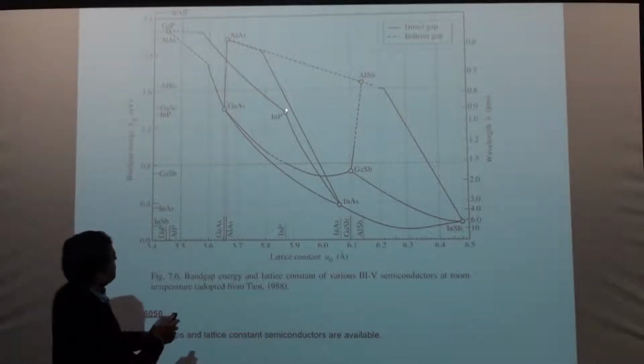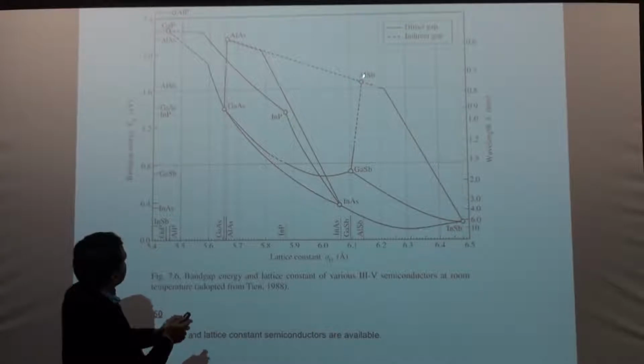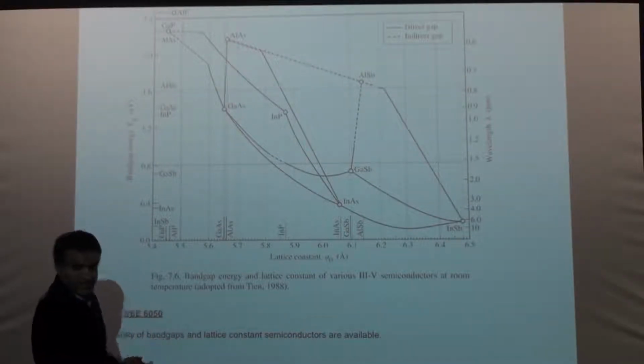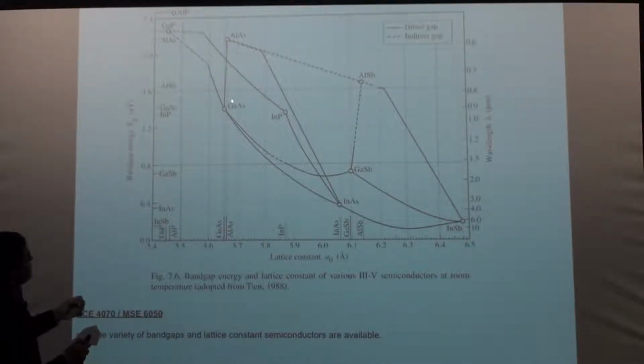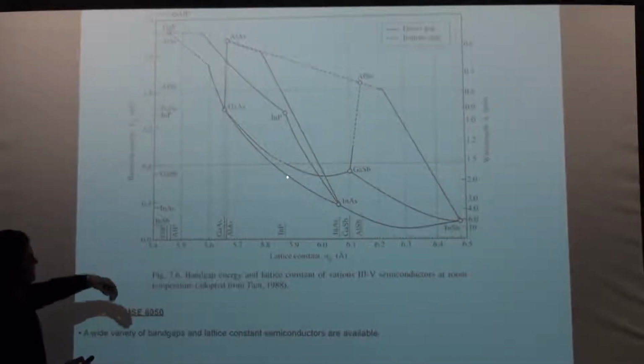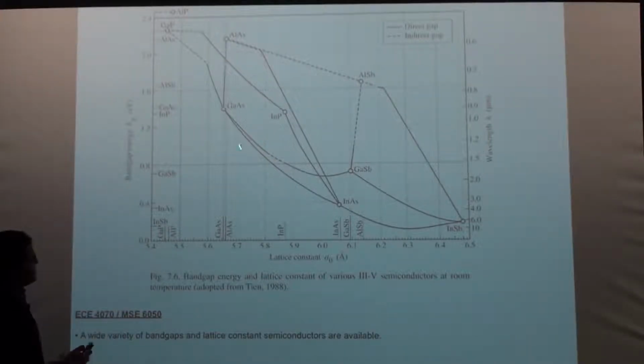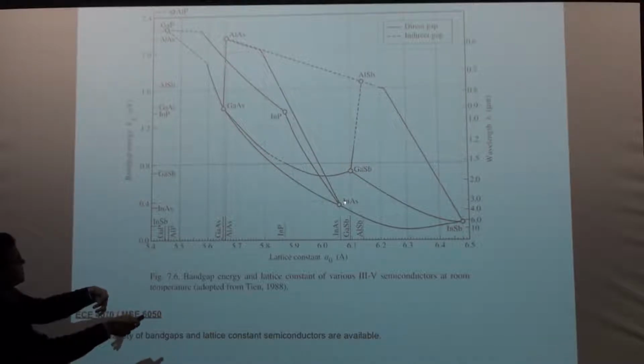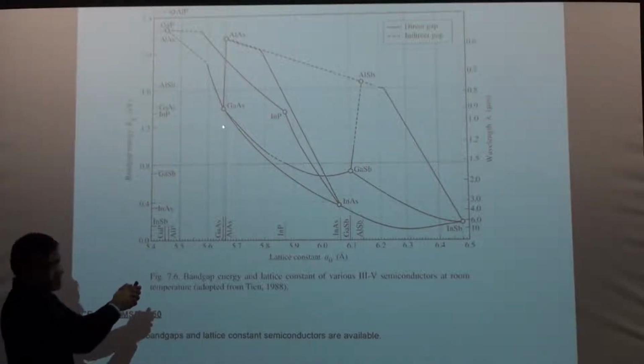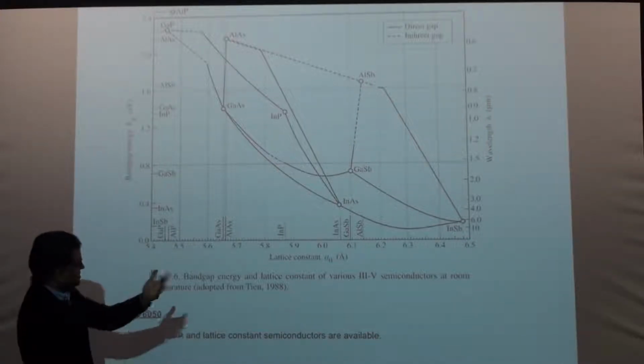And let's say I choose indium phosphide. Now on indium phosphide there is no other binary semiconductor that I can grow with no lattice mismatch. But you can see there are all these lines that are crossing it, right? And these lines are when, for example, I take gallium arsenide, and here's indium arsenide, and I can actually grow by epitaxy, like molecular beam epitaxy or chemical vapor deposition, an alloy of these two materials. So for example, let's say 50% indium, 50% gallium, and arsenic. So 50% of the metal sites, the group 3 sites, are occupied by indium, and the other 50% by gallium. Right? And so you have an alloy of indium gallium arsenide. It's InGaAs, that's the name used.